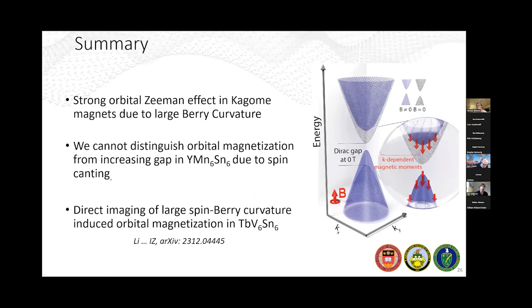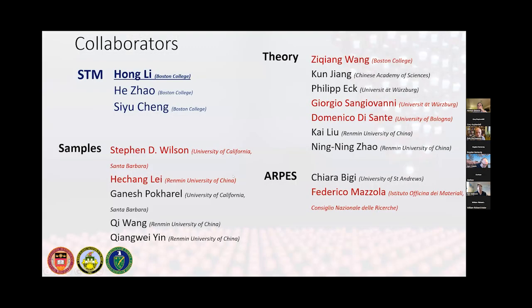Since I'm basically out of time, I just want to briefly summarize that these 166 systems are very interesting from the perspective of STM and imaging how the electronic band structure changes with magnetic field. In the first system that I've shown you, we simply were not able to distinguish spin canting from any sort of topological effects. But in terbium vanadium tin, due to how the electronic band structure evolves to much higher field than any sort of coercive fields that exist here, we can nicely attribute this to the underlying Berry curvature effects that give rise to these topological orbital magnetic moments.